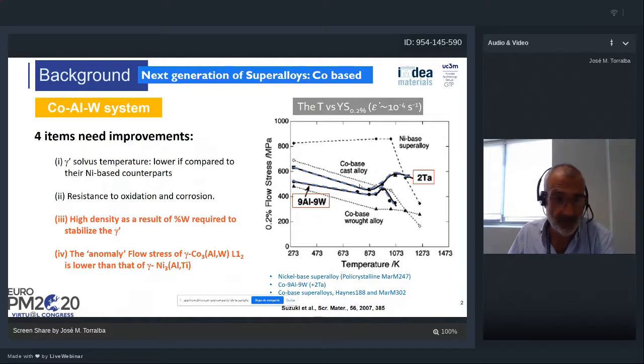The most important maybe is the high density of these materials, because in atomic percentage we have in the order of 9% of tungsten. So it's interesting to reduce the tungsten in the composition. Also the anomalous flow stress of the gamma prime precipitates is a little bit lower, as you can see in this picture, than the conventional nickel-based superalloys. So that means that we have to do things to improve this behavior at high temperature.